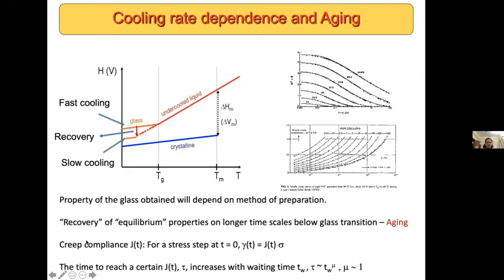And the response of materials to, as an example shown here, applied step stress, which would then lead to a time-dependent growth in the strain, characterized by this quantity called the compliance, is seen to change to larger timescales the longer one waits. And so the time to reach a certain value of the compliance, going from left to right in the bottom right figure, is longer and longer, the longer one waits. So there's a dependence on the waiting time of the properties, and this is something that's of great interest. And I won't say more about this. I just wanted to point to it as an interesting part of glass phenomenology.